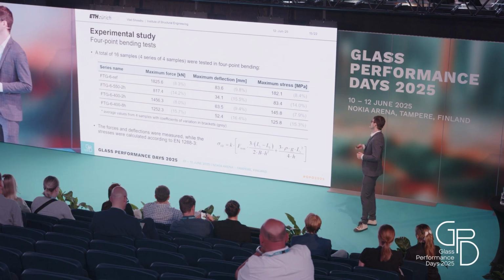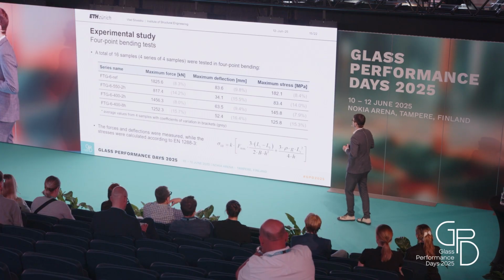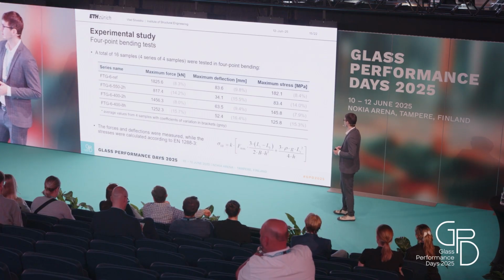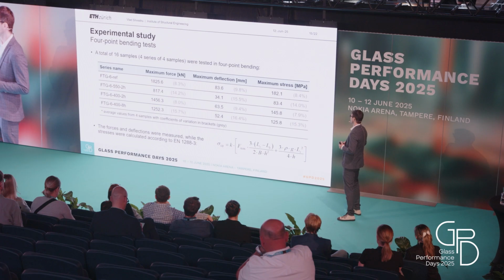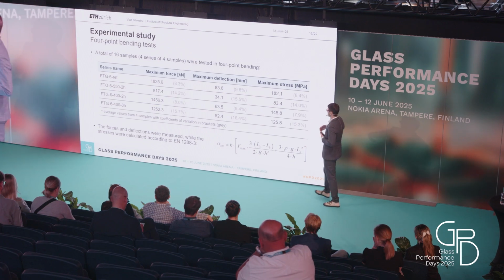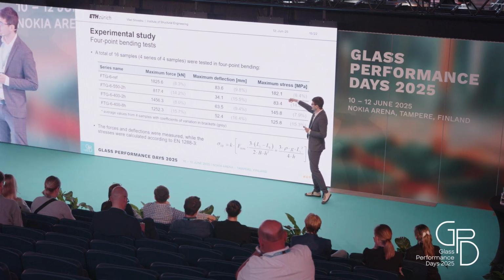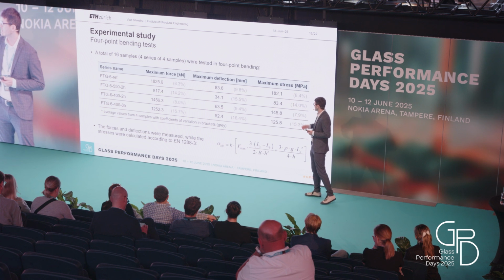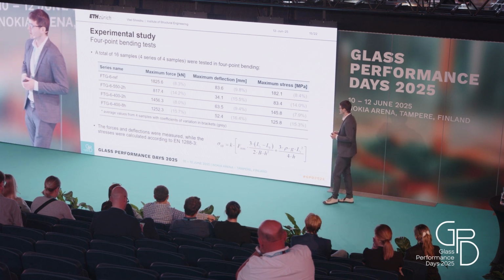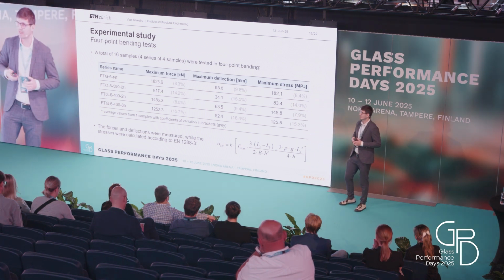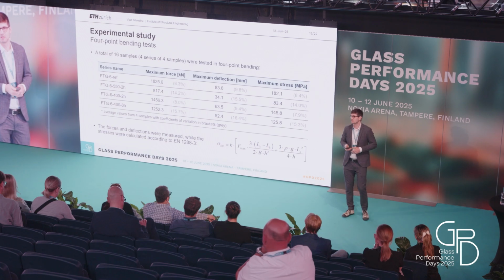From the force, we then calculated stresses. Since I only had 4 samples per test series, it didn't make really sense to do a statistical evaluation, but it was, I think, sufficient to compare the stresses, the reduction in bending stress that we obtained. And also here it can be seen that the reduction after treatment at 550 degrees was significant. At 400 degrees, it was in line with what we measured for the residual stresses.